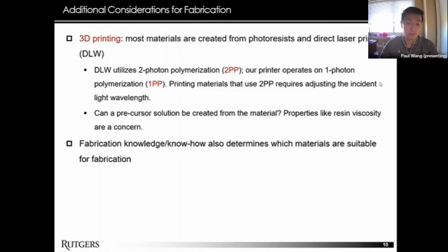Liquid resin solutions used in 2PP, they're called photoresists. They're meant traditionally for DLW printing. For reference, our printer uses 1 photon polymerization. Instead of 2 photons being absorbed at the same time, only 1 is absorbed. So as a result, our printer relies on a light projection instead of voxel, and it polymerizes cross sections to create a structure. To my knowledge, adapting a 2PP photoresist to our 1PP printer would require cutting the wavelength of the incident light in half. For example, if a DLW photoresist requires 700 nanometer wavelength light, we can print it on our system using 350 nanometer wavelength light.